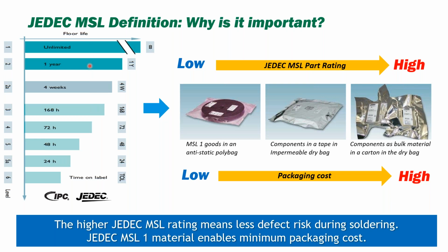So as it absorbs that moisture, the material gains the moisture, and then when it goes through the reflow process, that moisture or any other volatiles want to boil out of the plastic. So if the plastic isn't robust enough to resist that relatively rapid moisture exit, or it absorbs too much moisture, you don't have good blistering performance.